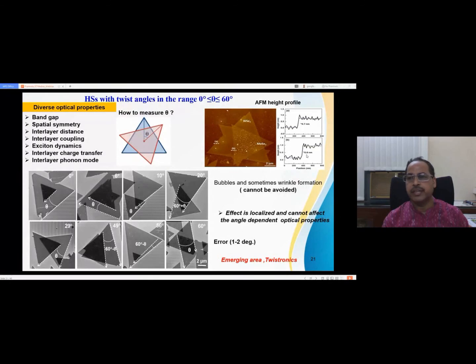So you can see it's 0.8 nanometer and this is 0.7 nanometer. So it is close to the one layer and then the other layer. But you can see this is a mechanical transfer process. This is not an in situ growth. So you cannot avoid some of the bubbles and the wrinkles will be formed, localized. You cannot avoid it. Although you are annealing it to increase the coupling strength between the two layers, it will be there, but it doesn't affect the optical properties.